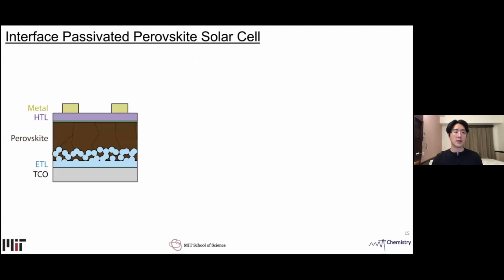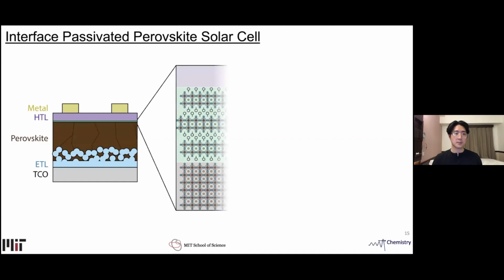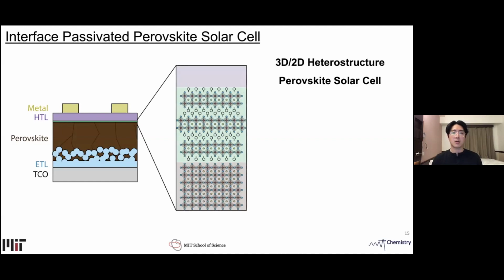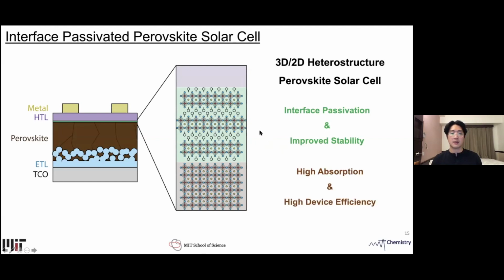So we can design a device structure such as the following, and we call it the 3D-2D heterostructure perovskite solar cell, where there is a thin layer of 2D perovskite responsible for interface passivation and improved stability. This bulk 3D perovskite is responsible for high absorption and high device efficiency.